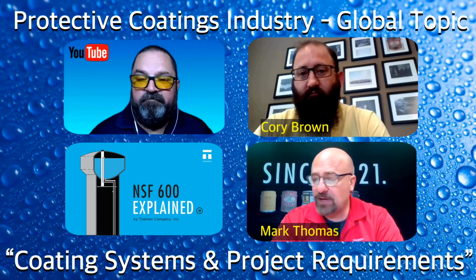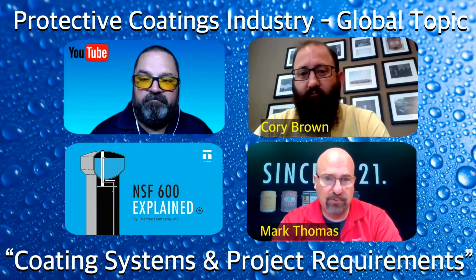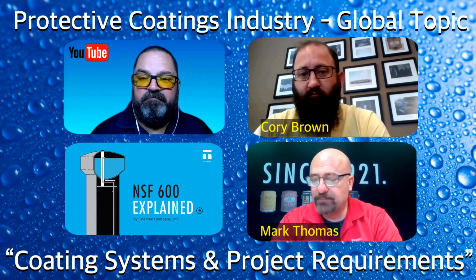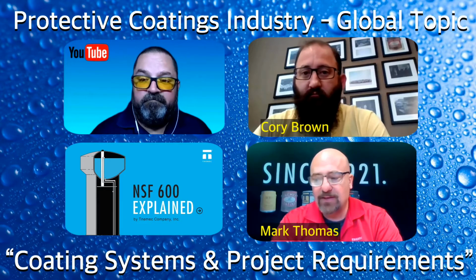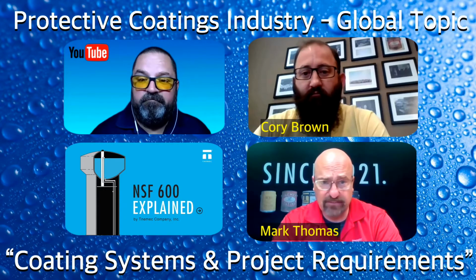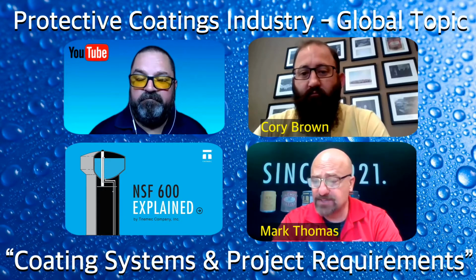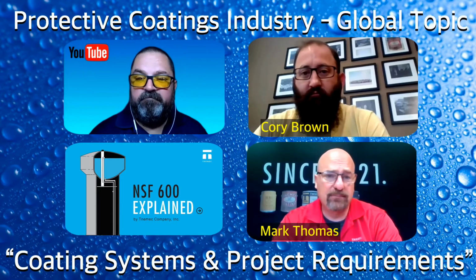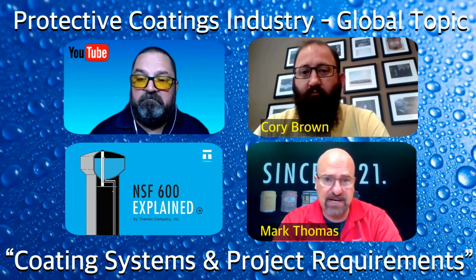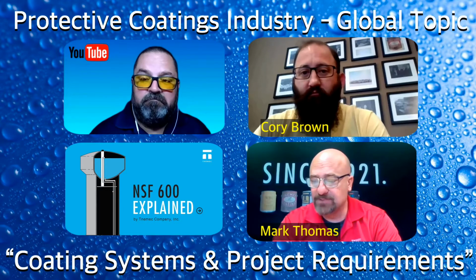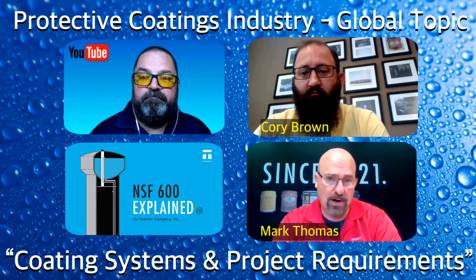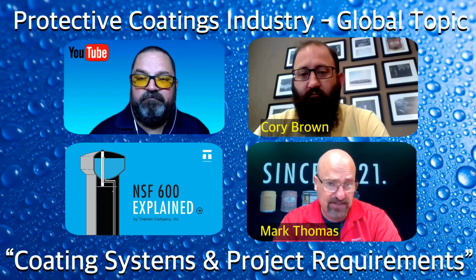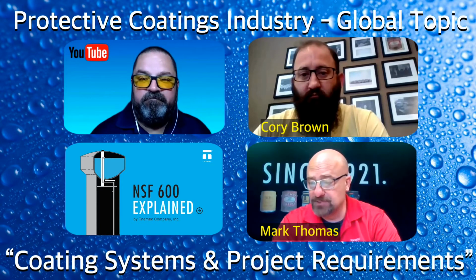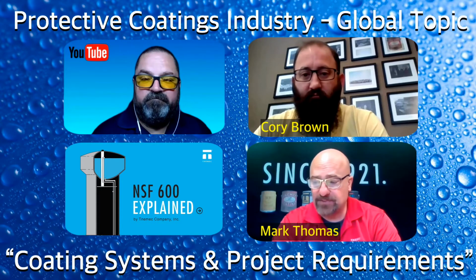And I was going to call out a few tests that we feel are really important to engineers. One is a basic immersion test. It's ASTM D870. It's a straight immersion test. We conduct this on all of our immersion grade products, and we run it with tap water. Our requirement is generally about 2 years in tap water with no type of adverse effects, or with deionized water, which obviously is a much more aggressive, smaller molecule that can get forced through the film. We usually run that for about 2,000 hours.